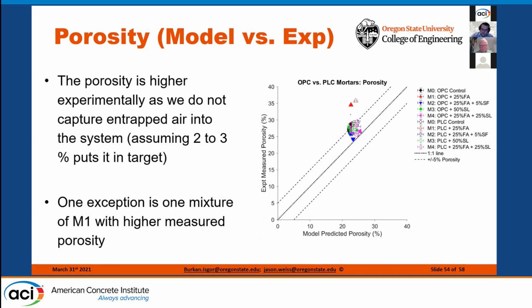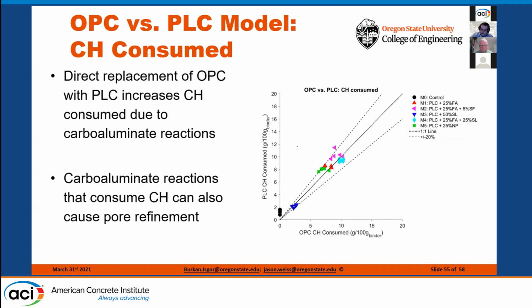If we compare the porosity from the model to the experiments, what we'll notice here is the model predicted porosity versus the experimentally measured porosity. We see that the experimentally measured is about 2% higher. What I do want to point out is that the model doesn't account for entrapped air. Once you account for 2 or 3% entrapped air, this is a direct comparison, and it works for every single mixture except for one mix where we believe there may have been some consolidation issues.